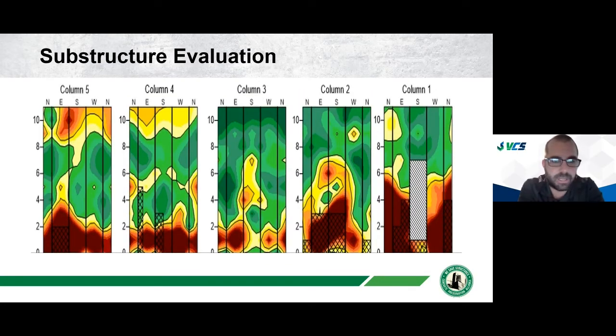And so doing that on those columns, you can see here are some examples. You can see the hatch mark is where the delaminations are. Obviously there are some areas of delamination, but then the hot areas are where active corrosion is beyond those delaminations. And you can obviously see that there's significant growth in the delaminations in, say, the bottom 4 to 6 feet of each of those piles due to their proximity to the salt water. And so this can help plan repairs. Like, okay, if we go out and just do patch repair, is that really going to address the problem? And clearly here you can see, no, if we just address the patches that are needed, there's still plenty of active corrosion beyond that and it needs to be addressed.